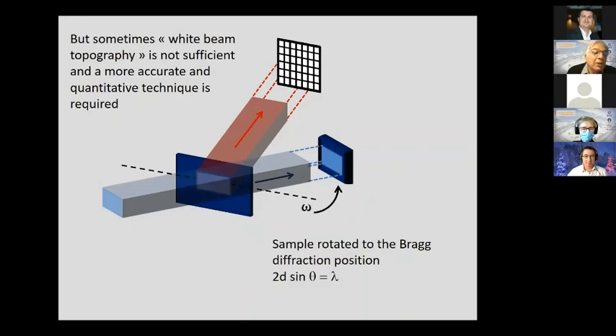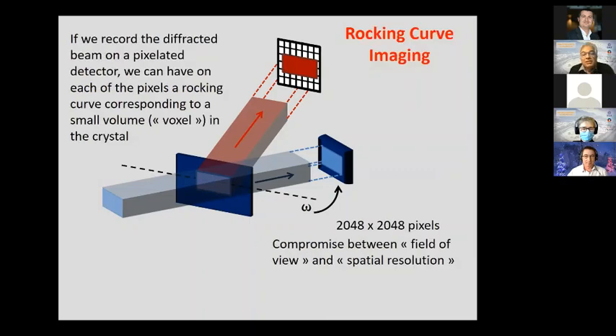But sometimes white beam topography is not sufficient and a more accurate and quantitative technique is required. So we have a monochromatic beam, and so we need monochromatic beam topography. In this case, we have to rotate the sample to the Bragg diffraction position, 2d sin theta equal lambda. If we record the diffracted beam on a pixelated detector, we can have on each of the pixels a rocking curve corresponding to a small volume in the crystal. So this is what we call rocking curve imaging.